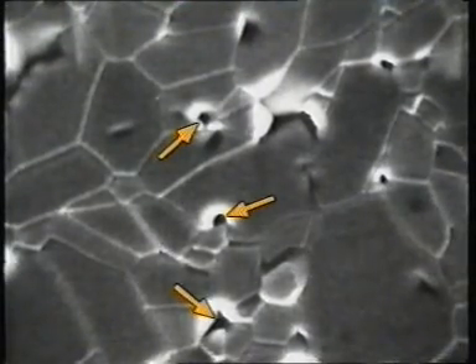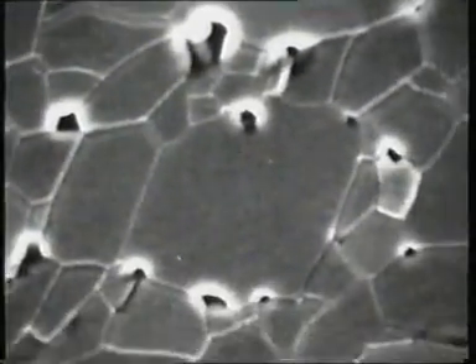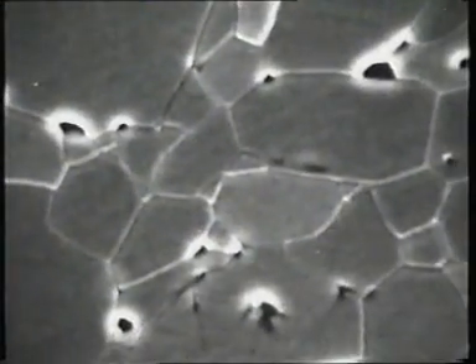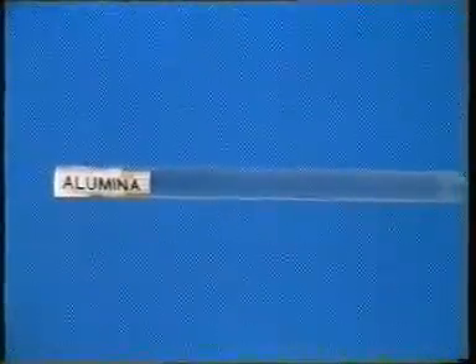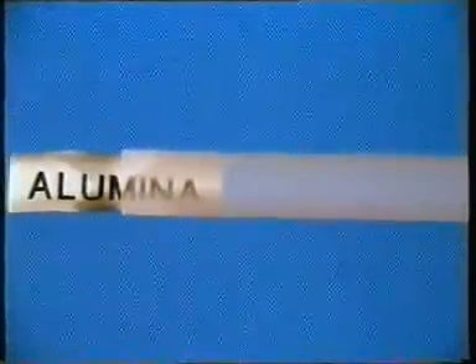When particles of alumina are sintered together, there are many voids left between them which cause porosity, as this micrograph shows. Light is scattered by these pores and grain boundaries, and very little light is actually transmitted. Alumina can be sintered into large crystals with no voids, and the tube becomes transparent but cracks easily. This is because large crystals have different responses to thermal expansion in different directions. The solution: a compromise between transparency and grain size to give a high-density, translucent alumina.